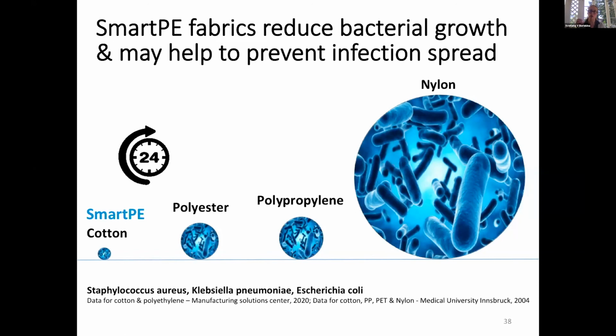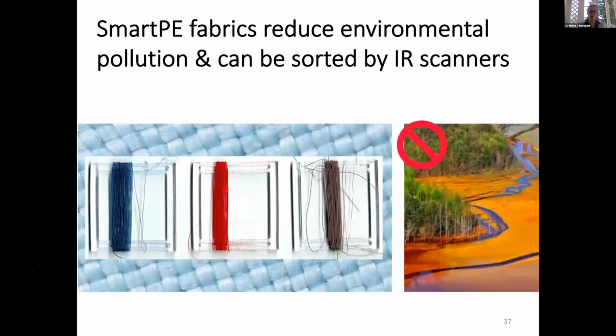But now we're doping the material, so this is, for example, doped polyethylene. It's not white anymore because of the stuff we put inside. We're doping it with known antibacterial and antiviral particles, which in many cases are just simple metal oxides, which get activated by the UV portion of sunlight, for example, and they literally kill viruses and bacteria. So that's the next step we're working on.